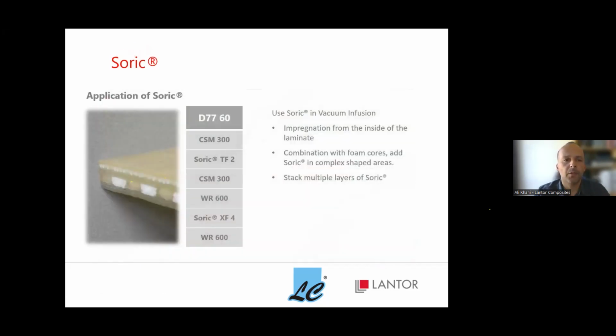Okay, so as we saw, we can use Soric in vacuum infusion, and basically what Soric does is that you can impregnate the laminate from inside. So the resin will flow through the Soric and then go to the top and bottom layers, which are close to the Soric. It can be combined with foam cores in one laminate. Also, you can use Soric because of its flexibility and drapability. You can easily use it in complex shaped areas.